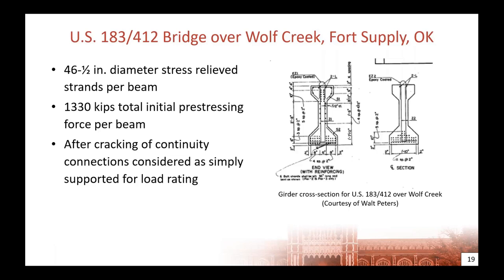This particular bridge had 46 1/2-inch strands, stress relieved. That works out to 1,330,000 pounds of pre-stressing. If you ever wonder why our bridges camber, just think about that million pounds of pre-stressing. After we had the cracking in our continuity, we tend to rate them as simple spans.